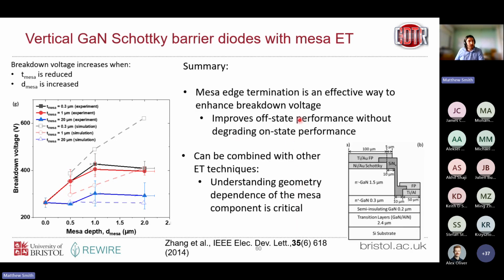So yeah, we've shown that MESA edge termination is an effective way to enhance the breakdown voltage, and it improves our off-state performance without degrading the on-state performance. We've shown how critical it is to consider the geometry. And what we note is that MESA edge termination is typically used in combination with other edge termination techniques, so field plating and dielectric deposition, that kind of thing. So this is by no means a cap on performance here, but we hope to see this type of understanding applied as a component of these more advanced MESA edge termination techniques.